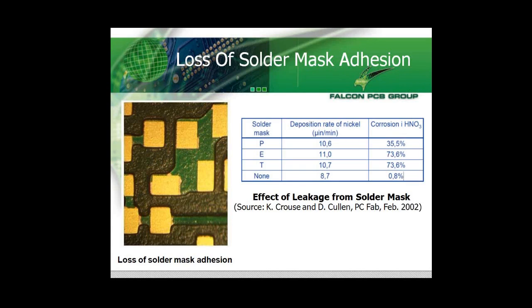The typical problem that occurs in practice is quite visible on the photograph on the left hand side, which shows the actual areas where the solder mask would start to lose adhesion around the actual pad areas.